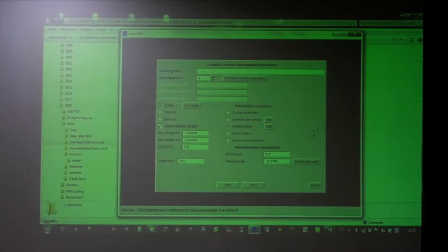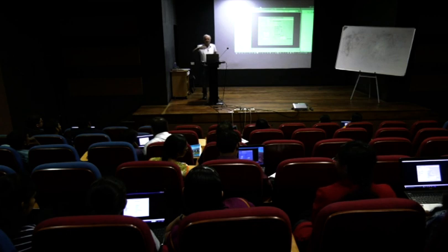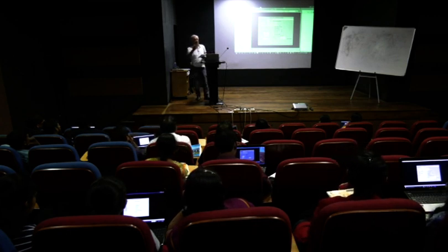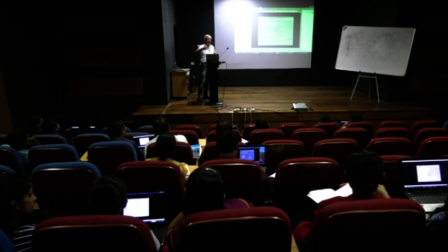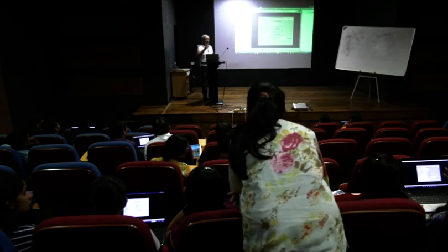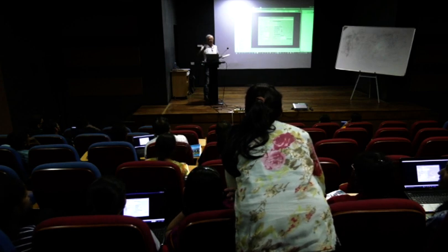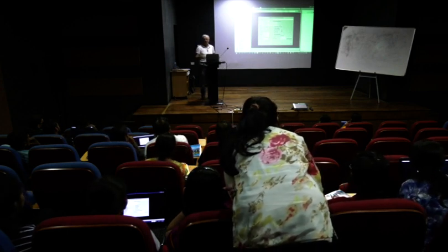I have chosen to start with, for example, cell parameters 3.8 space 3.8 space 7.0 and then 90, 90, 90. Now you have to go in with some parameters. It doesn't have to be exact. The more exact it is, the better the refinement will be, because if you're too far from your parameters, then the iterations take too long and they're not accurate.